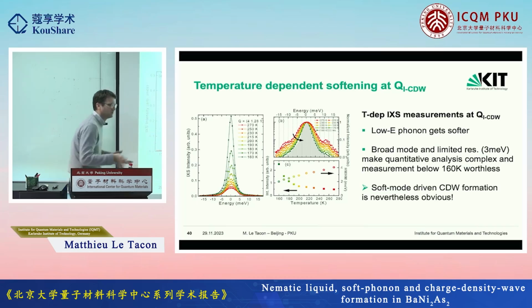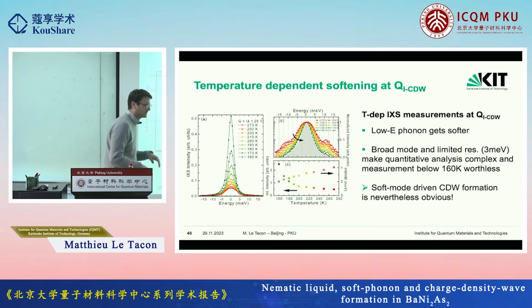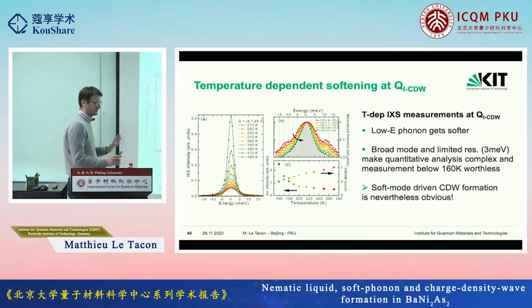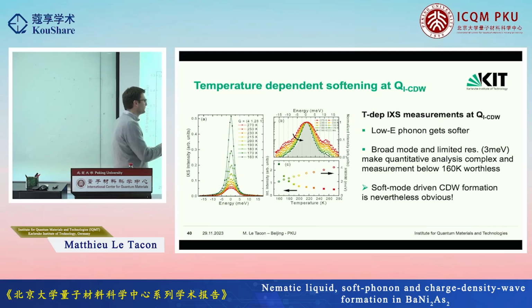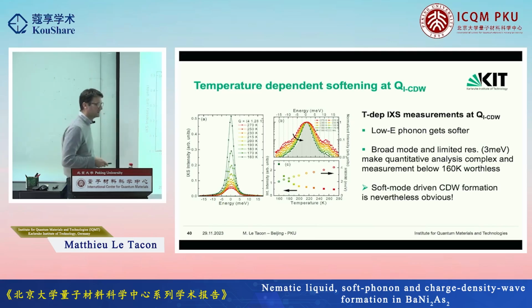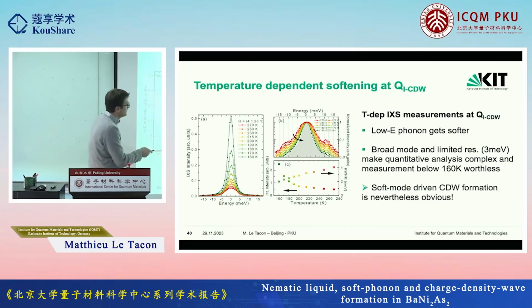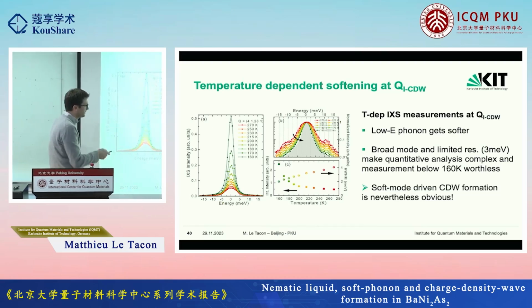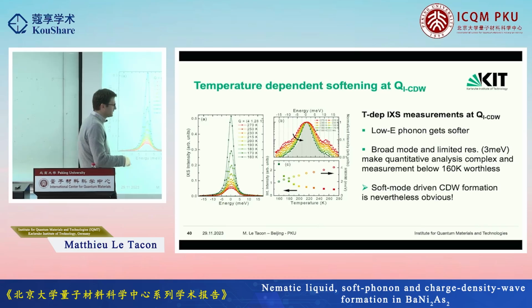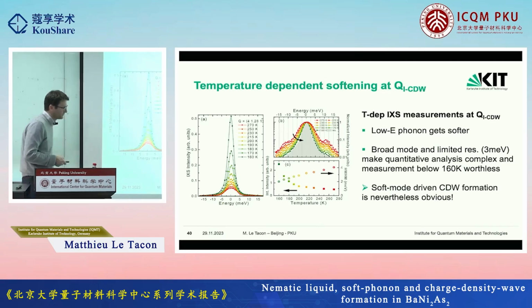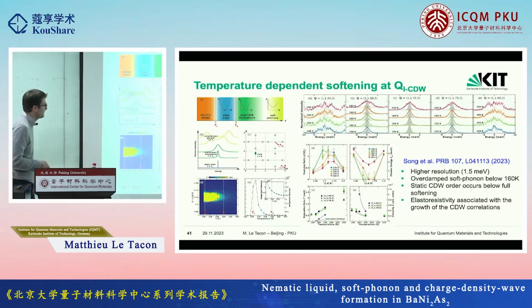I mean, you can get a number, I just don't believe it. You can get a slightly different number if you make a slightly different analysis. So I prefer to be conservative, say, well, the mode softens. And we try to constrain the fit quite severely with the spectral weight of the phonons and things like that. But still, below 160K, it's basically impossible to distinguish anything. You just get this very strong elastic line. So this is quite clear that indeed we are dealing here with a soft mode-driven charge-density wave.